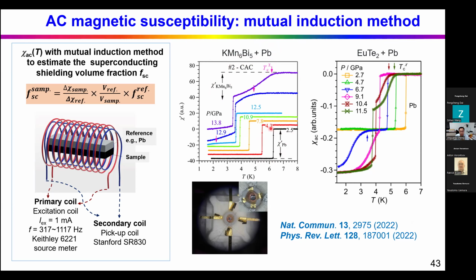For a type 1 superconductor, it shows a very sharp transition, and the TC will decrease with increasing pressure, but this drop doesn't change, so it keeps the same. But when this sample becomes superconducting, you will observe an additional drop. Normally, it's quite broad because it's a type 2 superconductor, and by comparing the magnitude of this drop, we can estimate the superconducting volume fraction. Actually, it's not the real Meissner effect. It's the superconducting shielding volume fraction. So basically, we use this method for our high pressure studies, and it works very well to estimate the superconducting shielding volume fraction.